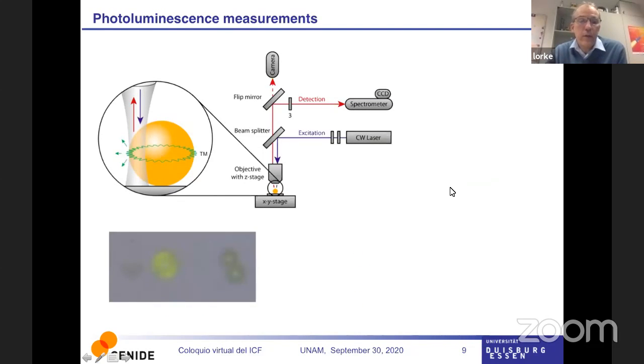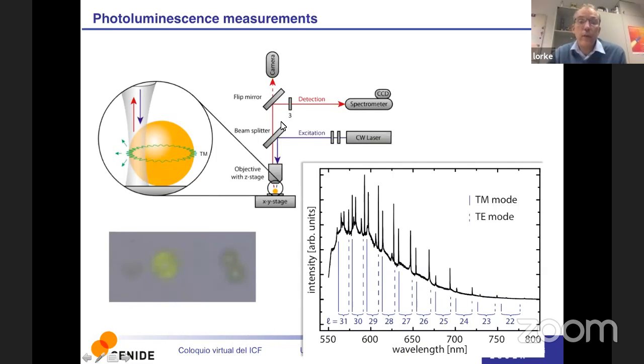Then they brought these spheres to us, and we put them under our micro-photoluminescence setup. That's why this picture is so small, because it's a micro-photoluminescence. Now in reality, it's much bigger. We have a laser that excites these spheres under a microscope objective, and the luminescent light is collected and brought into a spectrometer. You can also use the camera, and this is actually just a normal microscopic picture, and you can see individual spheres, and you can already see that they have quite nice optical properties.